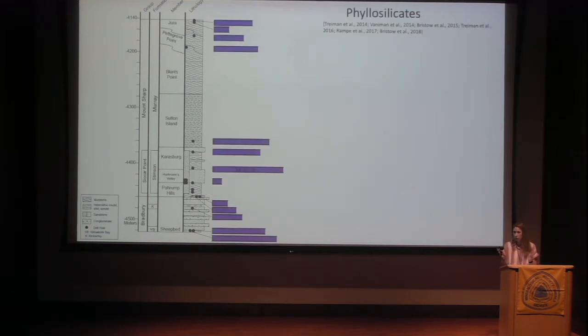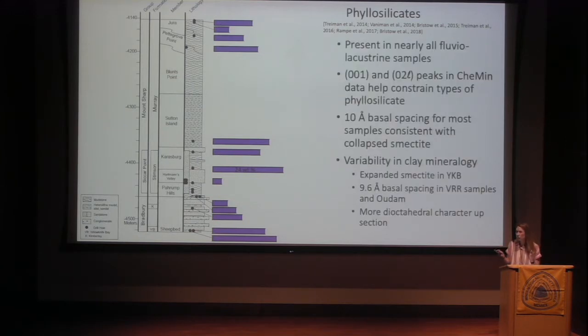Okay, the last mineral group I'll talk about are the phyllosilicates. We see them in almost every fluvial lacustrine sample, up to about 25 weight percent, but down to 0 weight percent in a few of these samples from the Pahrump Hills. We can use the 001 and 02l peaks to help us identify the type of phyllosilicates present. And in most of these samples, the phyllosilicates have a basal spacing of about 10 angstroms, which is consistent with a collapsed smectite.